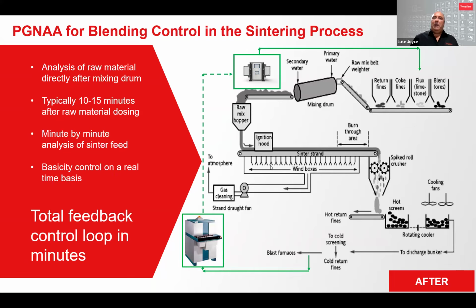So this process flow diagram shows the same process, but with a CB Omni Agile located before the sinter strand, enabling real-time control of the limestone addition to achieve a consistent calcium-silica ratio. The feedback loop is reduced to minutes. This results in a more efficient sinter process, which uses less energy and reduces the raw material costs.